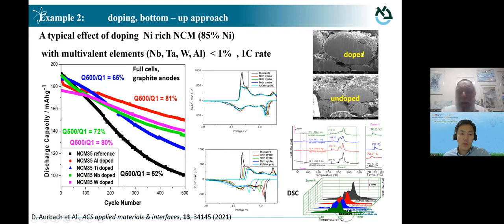This is cross-sectioning. It's cutting by focus ion beam, FIB, and then observation by microscopy. And we can see that when we have undoped material, when we have electrochemical instability, we have cracks after cycling, while the integrity of the active mass, the particles, is well maintained when we have the doping. So we have very nice correlation between all channels of stability and the electrochemical stability that we measure. So this means that we understand what is the mechanism of stabilization.